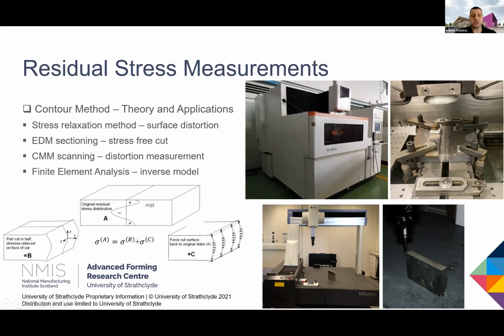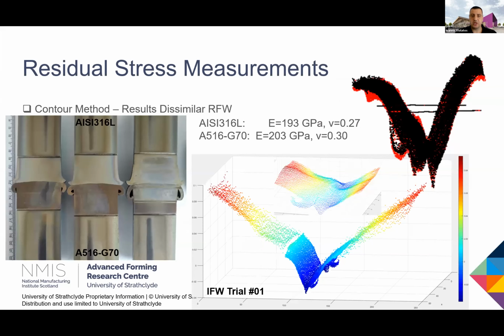However, we have other options as well, with the GOM scan or with Alicona if we are looking at much smaller specimens. And what we will do is take those distorted faces, invert them, apply that as a displacement field in a finite element model, and back-calculate residual stresses acting normal to that cut face. This is a very well established technique. We have developed quite a few things ourselves around that area, and we are very happy with the results that we are getting. We actually measured the stresses on all three samples following the characterization work.